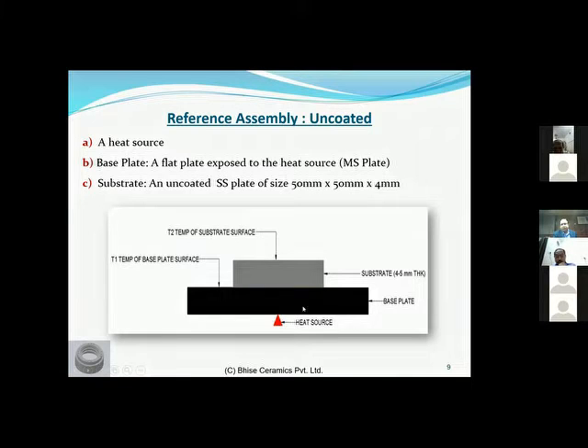Now, one of the roles that this base plate plays is that you really have uniform heating across the surface. So when you're conducting this trial, you have a very good idea of what the hot face temperature is and what the cold face temperature is.